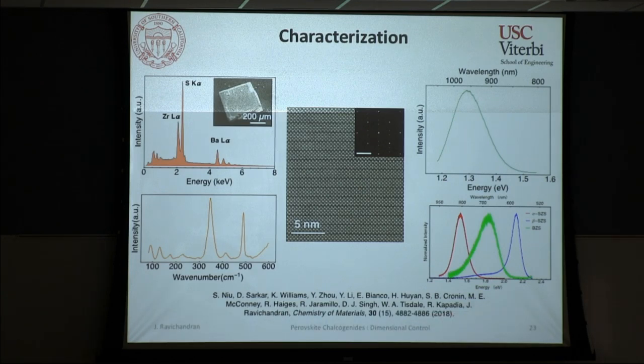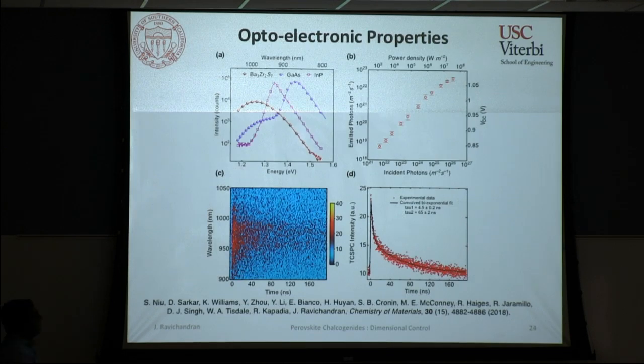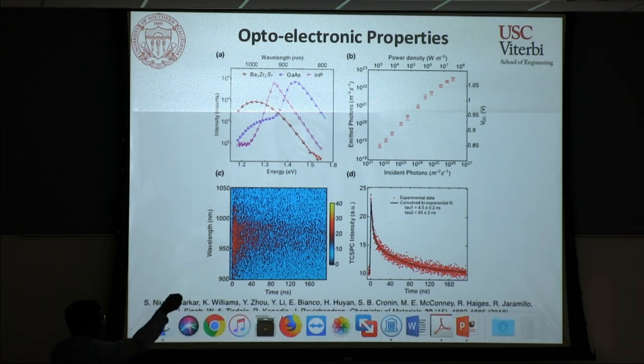We wanted to look at this compound more. So we did the same quantitative luminescence measurement similar to what we did for the beta BZS, and we can again show that the external quantum efficiency is a fraction of a percent, and that even though we have gone to the single crystal form, in this particular material we haven't improved the surface quality enough to improve the quantum luminescence efficiency significantly. Nevertheless, it's interesting that this does show pretty good quantum efficiency.